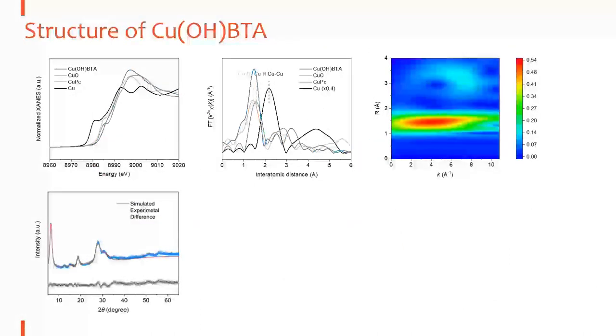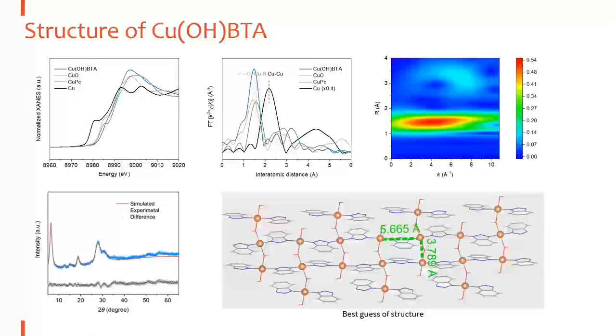So before doing that, we need to identify or clarify the structure of the copper BTA molecule. So we use several different spectroscopic approaches to characterize the structure of the material, like X-ray absorption, EXAFS, and also XRD to learn the structure and to model the structure. So finally, we get to what I call the best guess structure of this molecule. The reason we call it the best guess structure, not directly the structure, is because we do not have the single crystal data to support the structure. But this structure shows great agreement with all the experimental data, and it is also in line with previous literature reports.